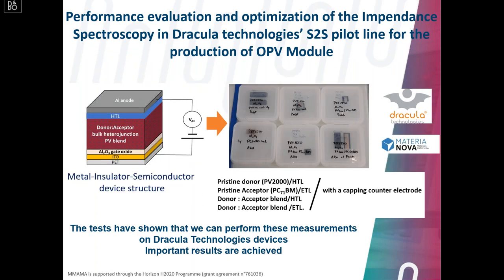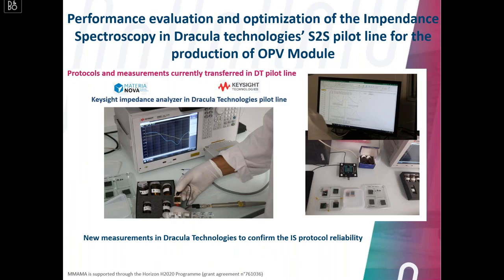So for that, we tried several times to realize some devices based on this device structure, the metal insulator semiconductor device. We made different structures in order to be able to extract all these parameters. And then with MATERIA NOVA, we made the measurement, and we demonstrated that this device can be realized, can be printed with the DRACULA technologies printer, and then we can determine all these important parameters in line in the process. Here, for example, we can see in this photo the Keysight impedance analyzers.